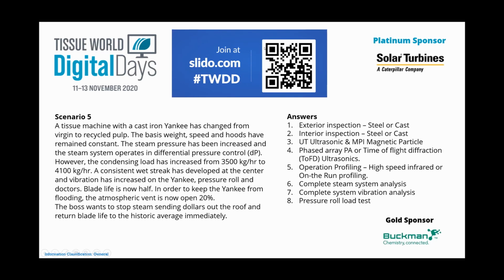So here we go. This is the one where the cast iron dryer has changed from virgin to recycled pulp. Recycled pulp has higher fines. The dryer is working harder, and the condensing load has increased from 3,500 kilos per hour to 4,100 kilos per hour. We now have a consistent wet streak at the center. Doctor life has dropped. And we have to keep the vent in the roof open in order to keep the dryer from flooding. So let's see what the audience said.